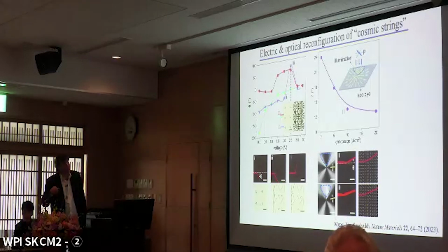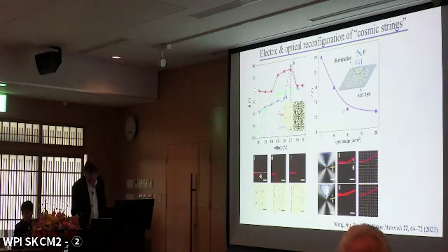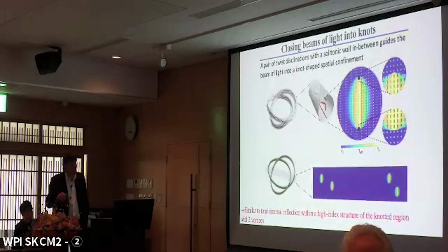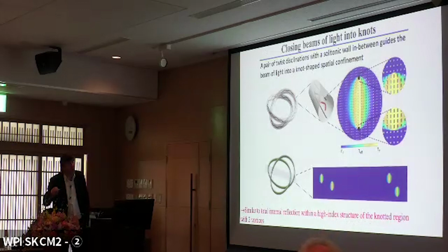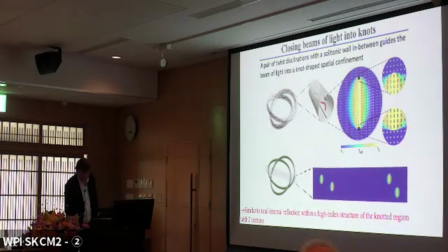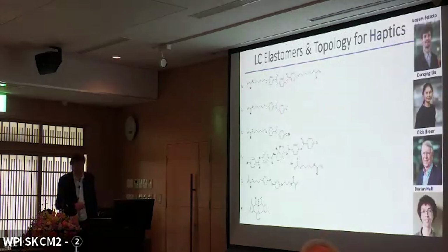Also, we can use light itself to redirect liquid crystal director around these vortices and then change these deflection angles as well. Moreover, in a chiral liquid crystal where we can stabilize twist solitons that can be kept by vortex lines in here, the twist disclinations, we can form knots of these and localize laser beams of light into not just closed loops, but also knot structures as well.